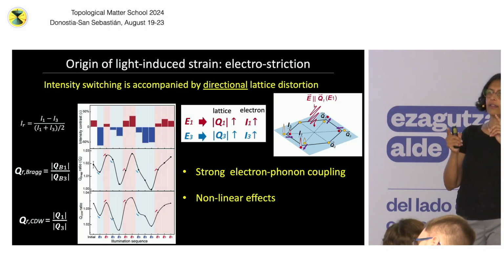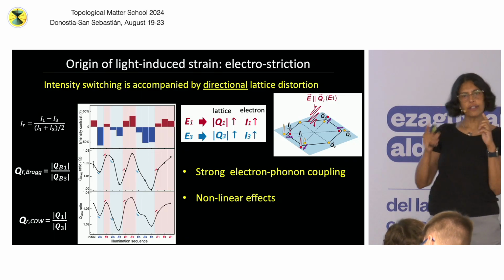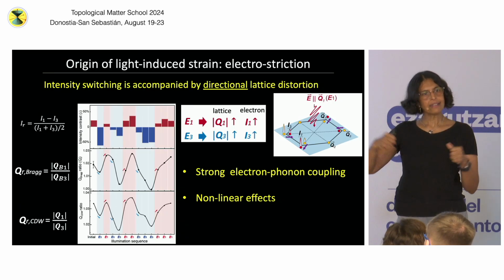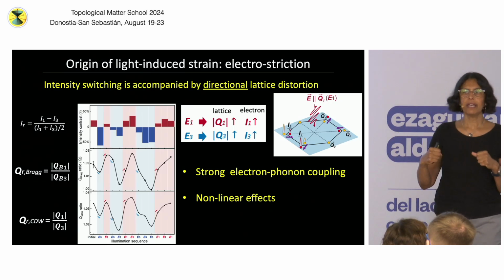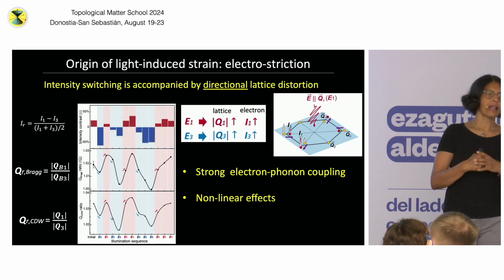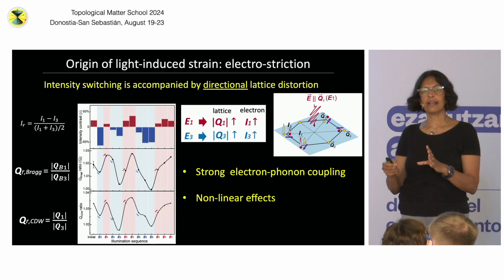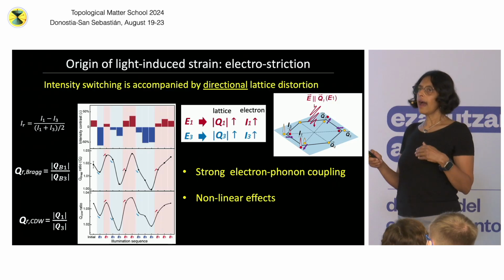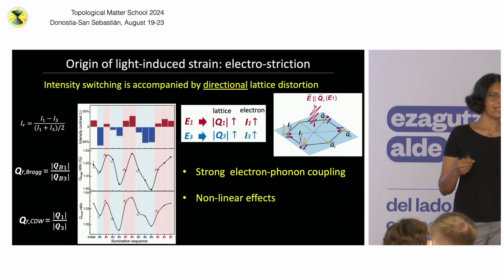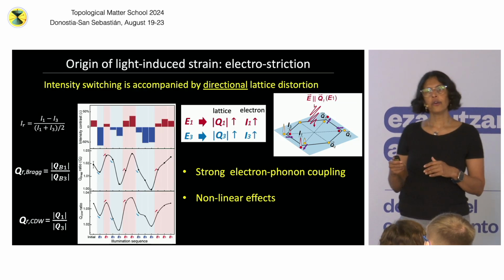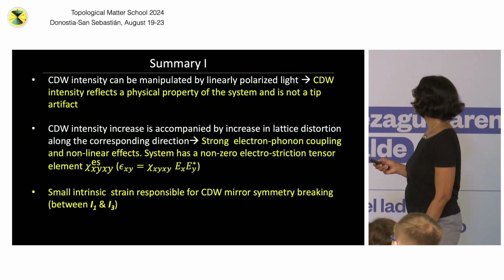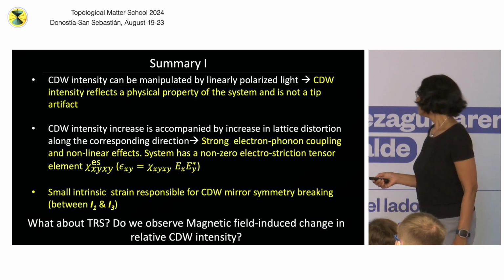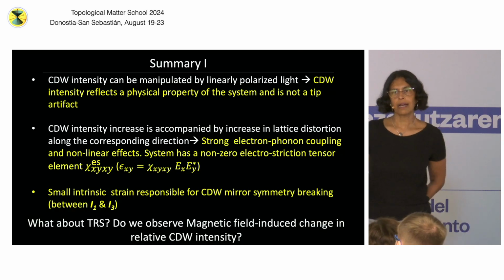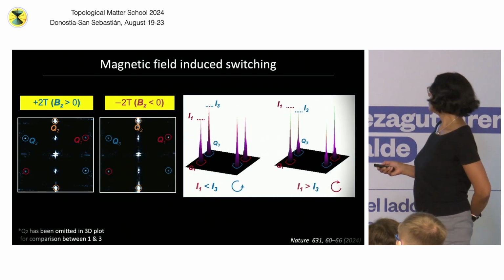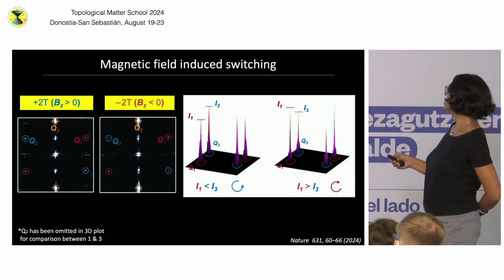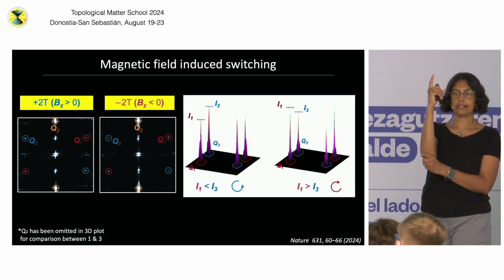So if one is higher than the other, there is some physical meaning embedded in that. The physical meaning is that the lattice distortion is larger in that direction, which means the amplitude of the order parameter is larger in that direction. So that's what our laser studies have told us. Now, armed with this knowledge of what the intensities mean, we can go back and look at the experiments with magnetic field. So we repeated the magnetic field experiments done by Zahid, and we see the same thing they do, meaning that in different directions of magnetic field, perpendicular to the sample, remember.